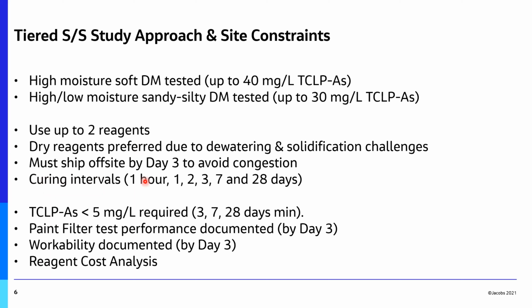And so when we looked at our treatability study, we looked at curing intervals of 1 hour, 1, 2, 3, 7, and 28 days. The early times to manage the materials and expedite their removal from the site, but 3, 7, and 28 days for compliance to ship offsite, and then long-term compliance at the landfill. So you can imagine you can develop a scheme where you passed the TCLP on day 3, but by 28 days it failed at the landfill, and then it was a problem at a landfill. So we had to demonstrate that whatever we met at 3 days at least lasted through 28 days when the material was fully cured, okay?